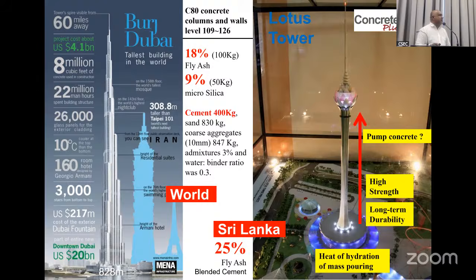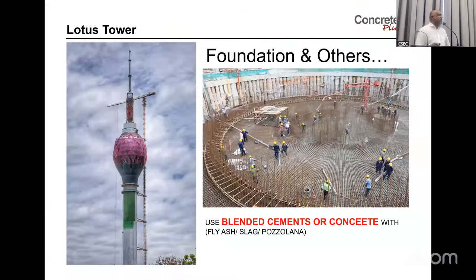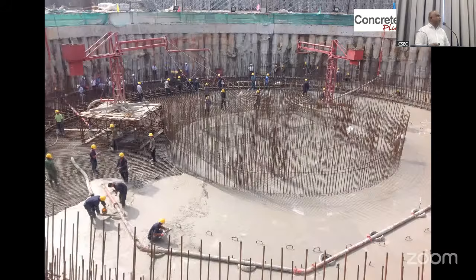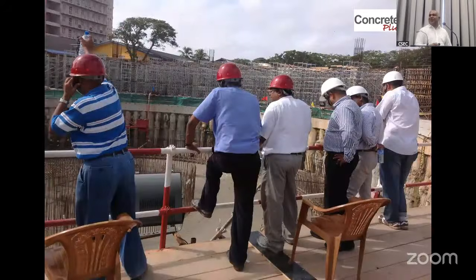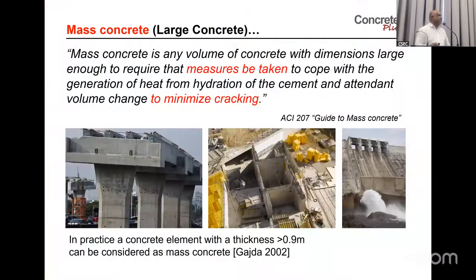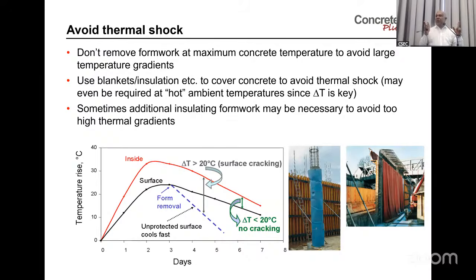So these are some of the structures. In the total structure, we have used 25% fly ash. This is a very good photo they have taken. This is what I told you about mass pouring. In mass structures, you need to stick to two things. One, the temperature at any given point should not exceed, very roughly, 70.